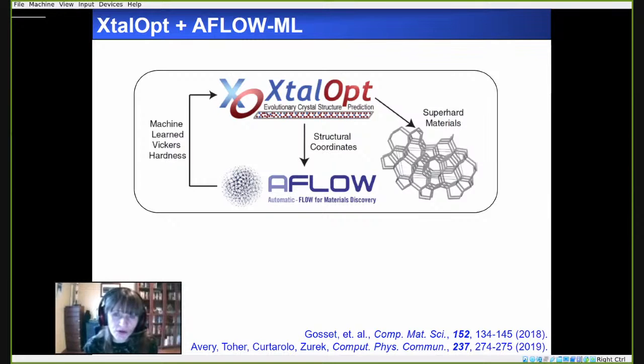So the way that this works is we use XtalOpt to create new structures, optimize them to the nearest local minimum. We send out the structural coordinates to AFLOW. AFLOW then determines the bulk and shear moduli using the machine learning model, and XtalOpt will then use these bulk and shear moduli to determine hardness and use that in accordance with enthalpy to determine which structures are the most stable for breeding within the evolutionary crystal structure search.